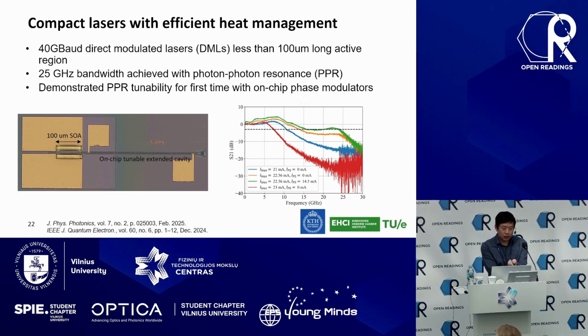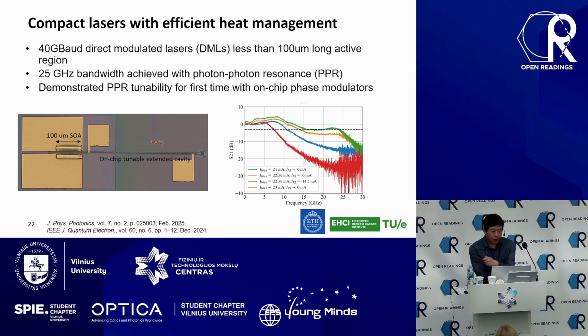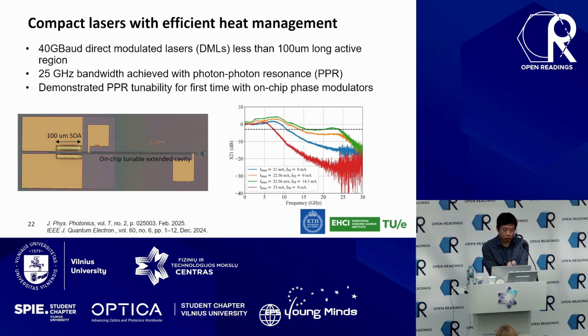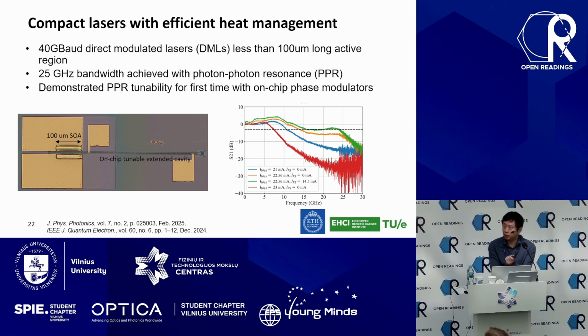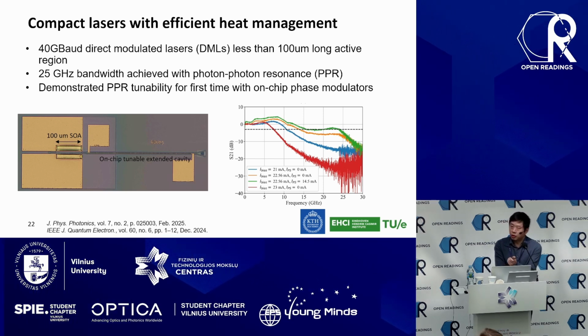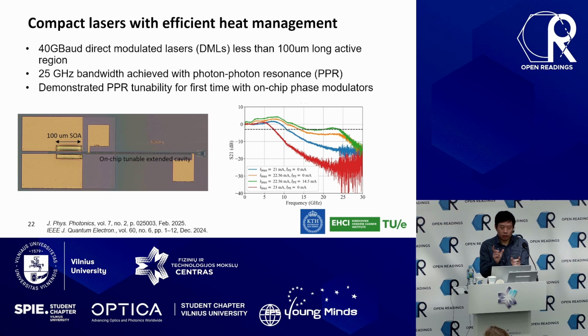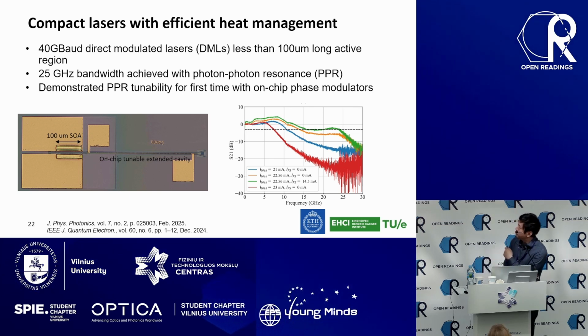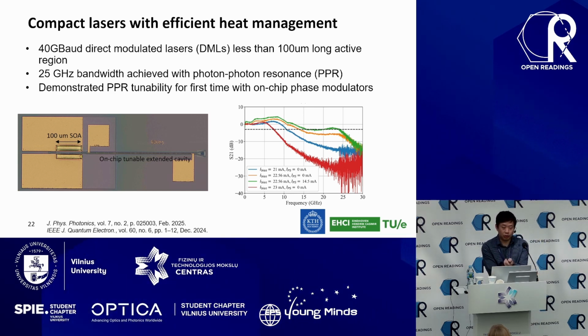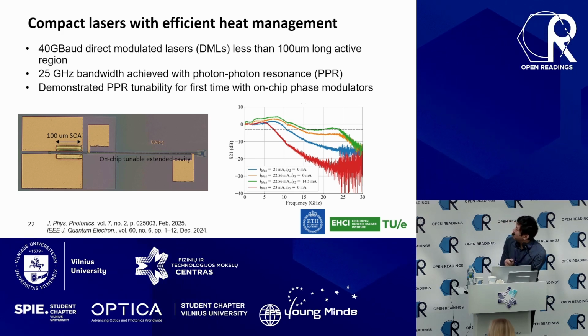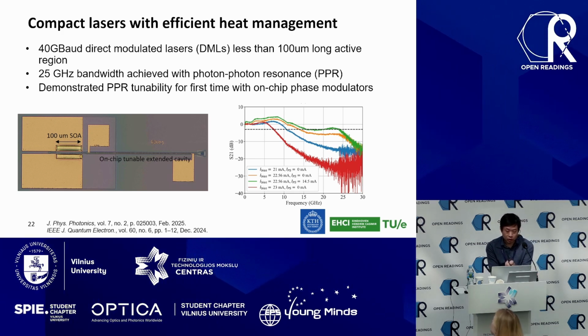As you can see, now we can build a very compact laser where the SOA, the amplifier in the laser, is only as short as 100 micrometers. And we also create an external cavity on the right side with an on-chip phase shifter, where we can fine-tune the coupling between the main cavity and the extended cavity on the chip. And by doing this, we observe that we can extend the bandwidth of your laser by several folds.